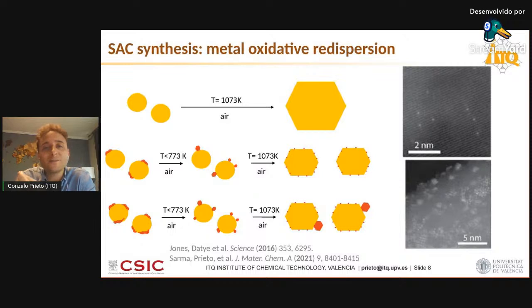You can see there as bright speckles those isolated metal centers supported on the crystalline, in this case, oxide support material. Actually, the trapping of these metal species by the oxide support lowers the surface energy of the whole system, and it prevents the sintering of the support itself, which could have happened should we treat this support without any additional metal at these very high annealing temperatures. That's what I'm showing in the top side of my cartoon. That's the sintering which would have happened if there were no monoatomic metal species being trapped and therefore reducing the surface energy of the whole system.